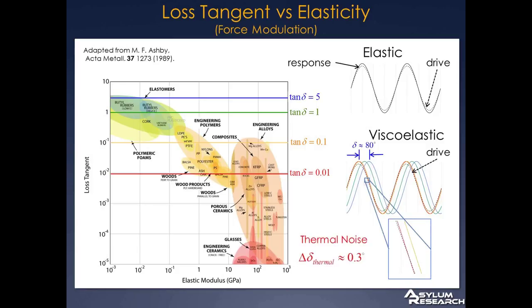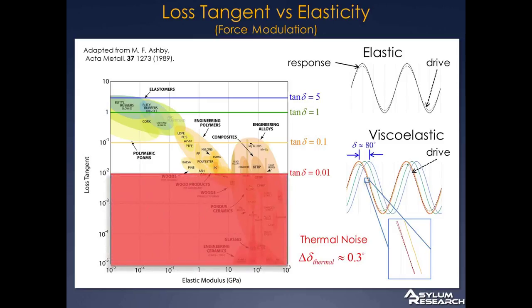Now, this is interesting because if we're poking on this, or applying this force with a cantilever, the cantilever is going to have some measurement noise. For a typical AC240 cantilever, the thermal, the Brownian motion of that gives you a phase angle error of about 0.3 degrees. What that means is that for that AC240 cantilever, the loss tangents below that red line there, the 0.01, are basically not accessible. They're masked by the experimental noise.